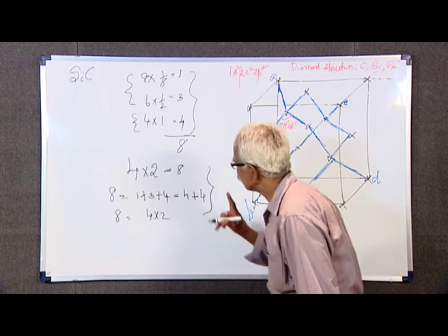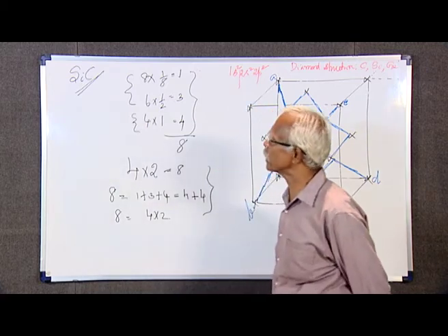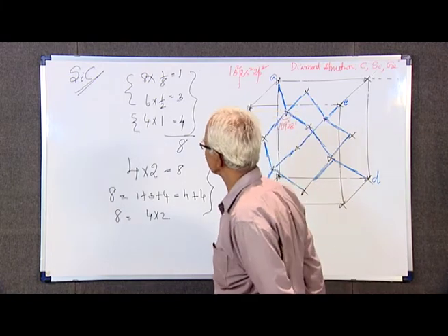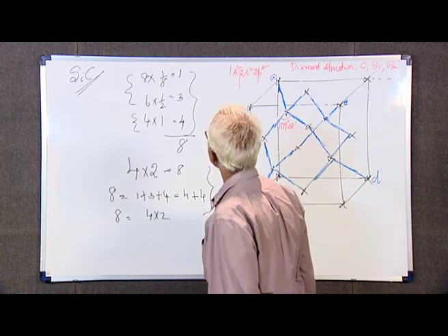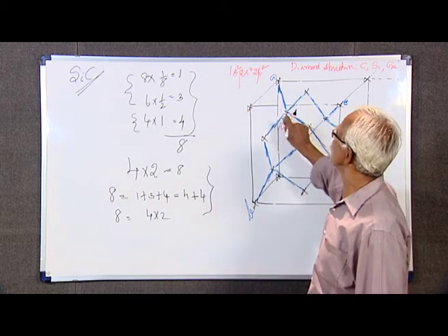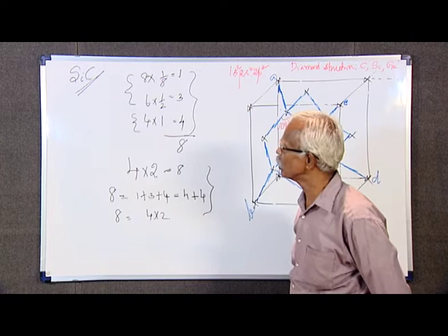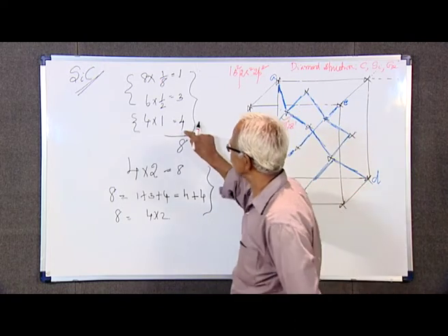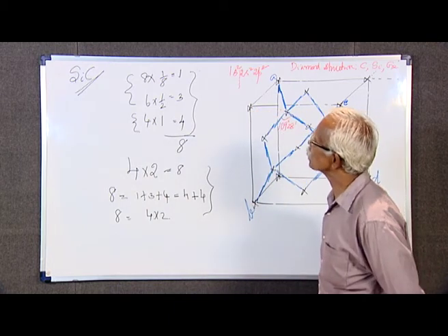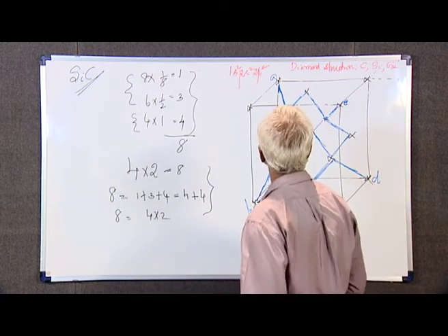This will give you the answer how to accommodate the silicon and carbon atoms in carborundum, in silicon carbide. The simplest answer is you accommodate one species at the corners and face centers, so that you will have 1 plus 3, 4. You accommodate the other species at the unshared 1/4, 1/4, 1/4 positions. So that a silicon carbide crystal will look like this.